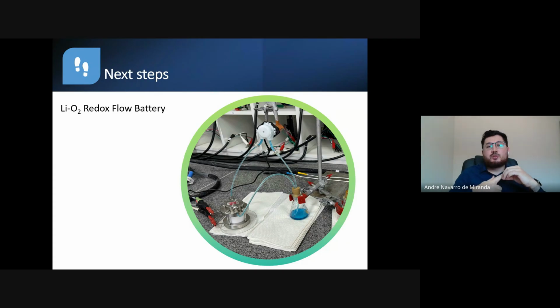So one of the ideas is to use lithium-oxygen redox flow batteries. So what's the idea here? We kind of circulate, so here's a pump that pumps the electrolyte into the battery here, and then it goes on and goes on between all the discharge process of the battery. So the idea here is when we circulate the electrolyte over in the battery, we kind of recover the lithium peroxide from the cathode, and then we free the active site to react again. So we can get the peroxide out of the cathode during the discharge process, and then we decompose the peroxide in the charge process.